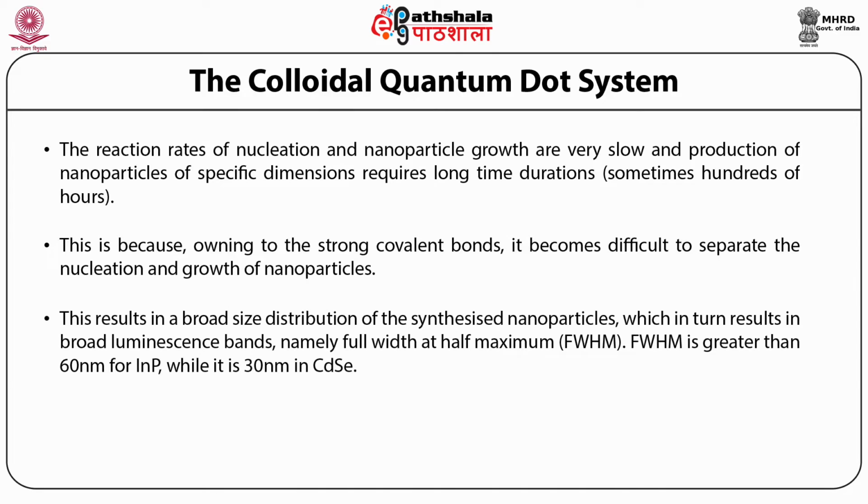This results in a broad size distribution of synthesized nanoparticles, which in turn results in broad luminescence bands, namely full width at half maximum. FWHM is greater than 60 nanometers for indium phosphide, while it is 30 nanometers in cadmium selenide.